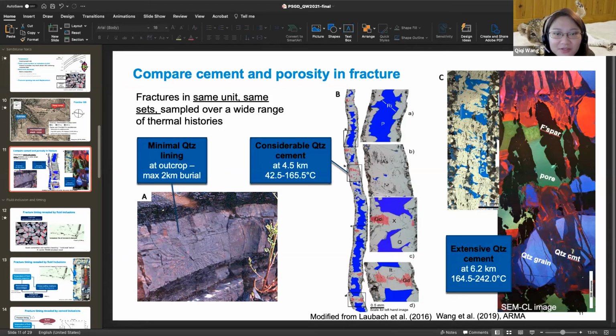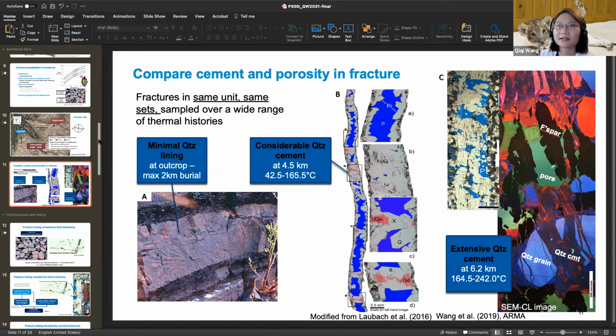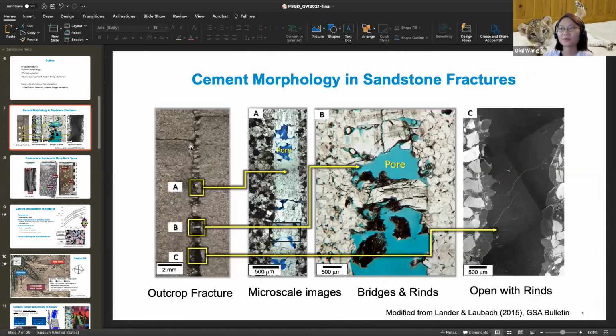There are all sorts of patterns. And in terms of fracture connection points, I would say when two fractures start to grow towards each other and they see each other and eventually link, those connection points are usually smaller aperture compared to, for example, the middle part of the fracture. I think I'm showing you examples right here. This is how fracture aperture and cement texture vary from the center wider part of the fracture all the way to the tip of the fracture, right? Oh, sorry, am I sharing my screen?